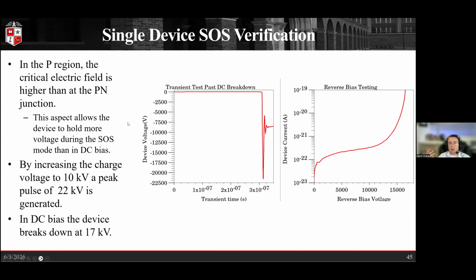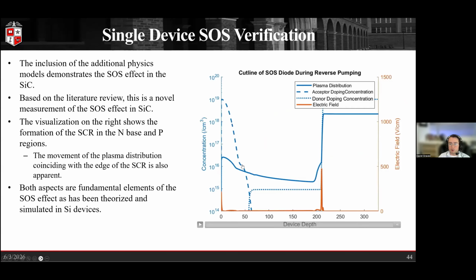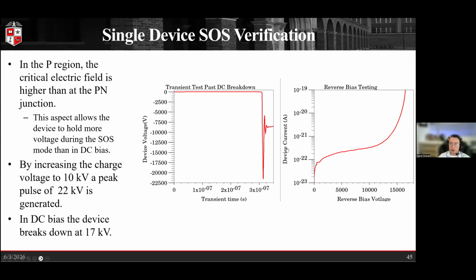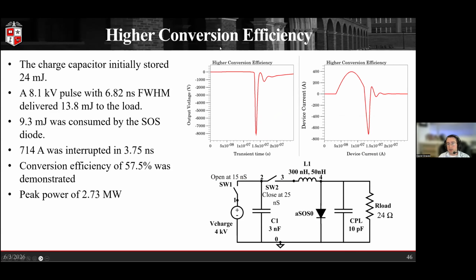So now if we were wanting to look at the breakdown voltage of the device, we can see too, that because we have the space charge region actually being formed in the high doping region rather than the base, we're able to actually have a higher breakdown voltage. And so during the pulse, even though in DC we're only able to hit 17 kV, if we charge the device with 10 kV, we can get a 22 kV pulse out, going beyond the DC breakdown. Now looking quickly at the higher conversion efficiencies, if we optimize the circuit again, we can do basically the same thing as before, but now we're able to get a conversion efficiency of 57.5%. So we're delivering most of the energy to the load rather than dissipating it into the diode. As we can see here, we're only consuming 9.3 millijoules of the initial 24 millijoules that was given on the capacitance.